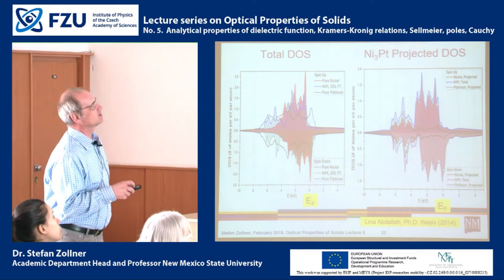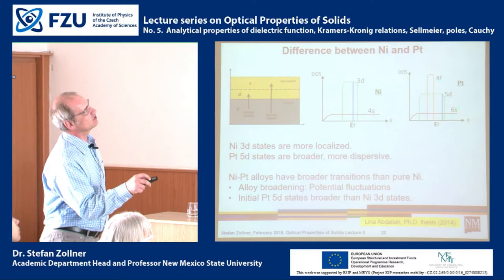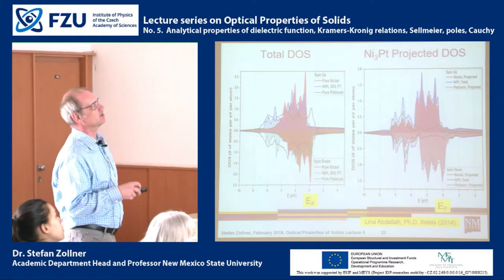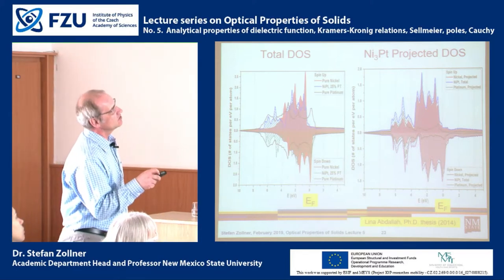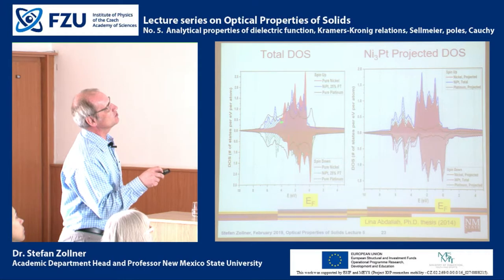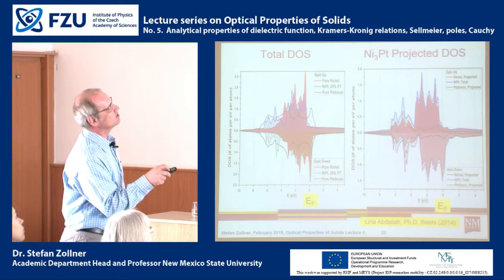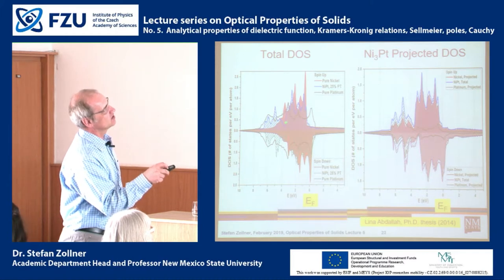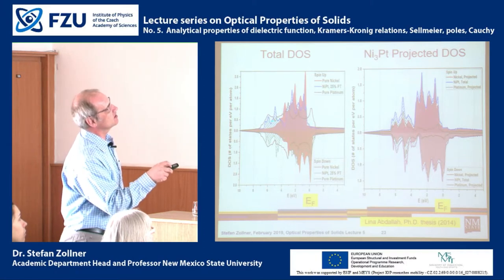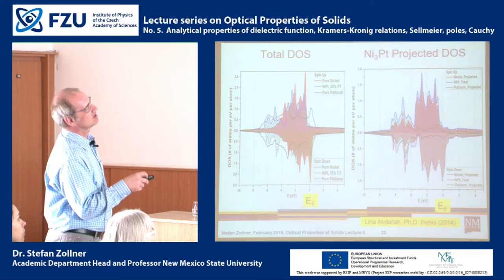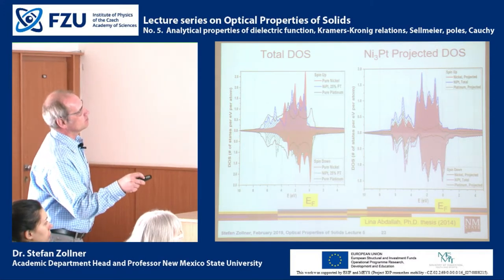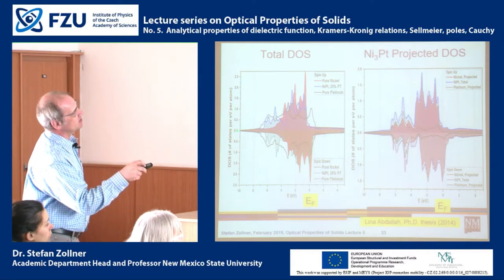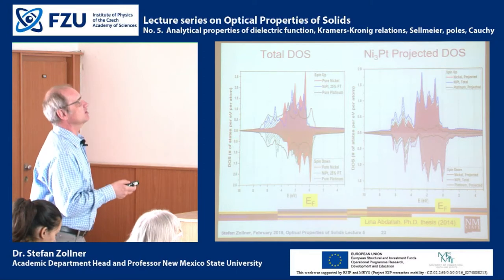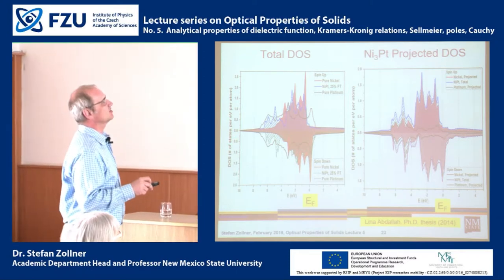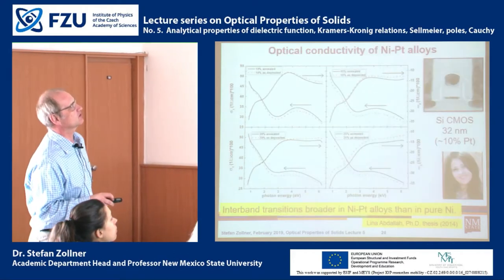And we can also look at this more quantitatively, instead of looking at this cartoon, by looking at calculated density of states. In red, you see the density of states for pure nickel, and in black, you see the density of states of the 5d states in platinum. So you see the bandwidth of the nickel 3d states is only about half of the width of the platinum 5d states. The very narrow cones here are the highly dispersive s states, the contribution of the s states to the density of states.